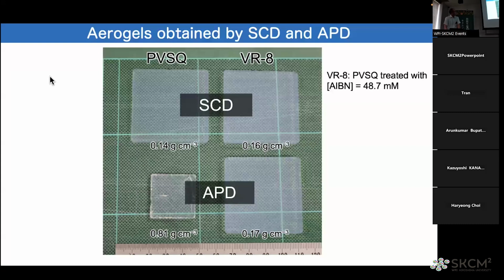So in this process, this is a pristine vinyl functionalized gel with the supercritical drying. Of course, you can prepare the aerogel, but with ambient pressure drying, there is a lot of shrinkage. Most of the pores are collapsed. But after the treatment and ambient pressure drying, you can see spring back behavior, and you can prepare nice aerogels.